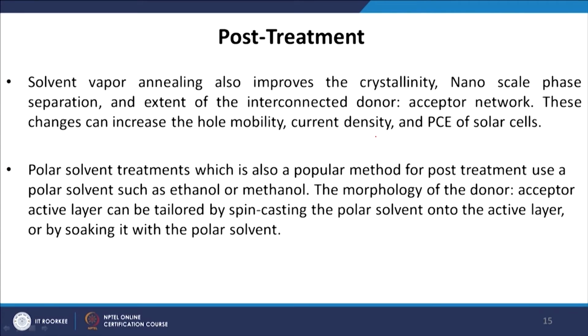Polar solvent treatment, which is also a popular method for post treatment, uses a polar solvent such as ethanol or methanol. The morphology of the donor acceptor active layer can be tailored by spin coating the polar solvent onto the active layer or by soaking it in the polar solvent.